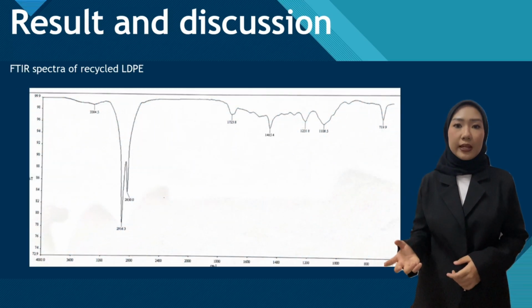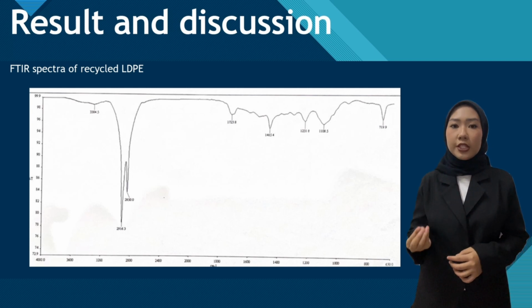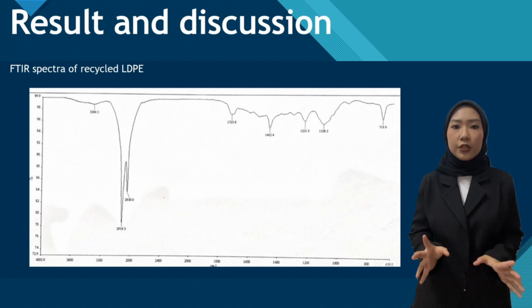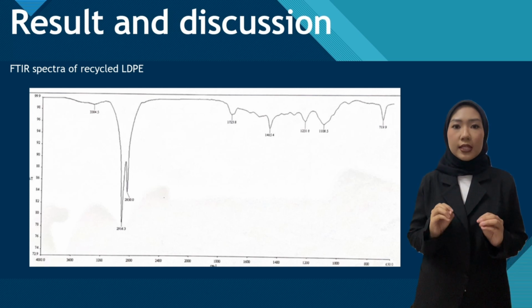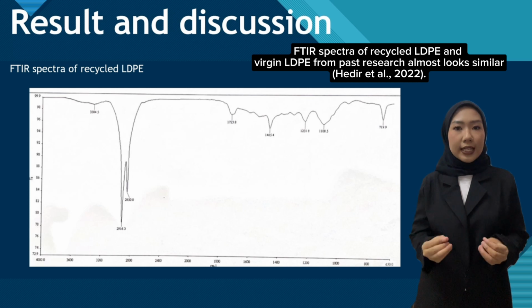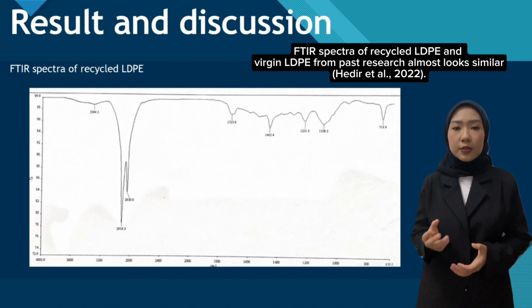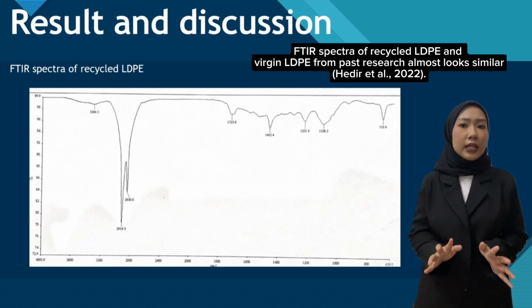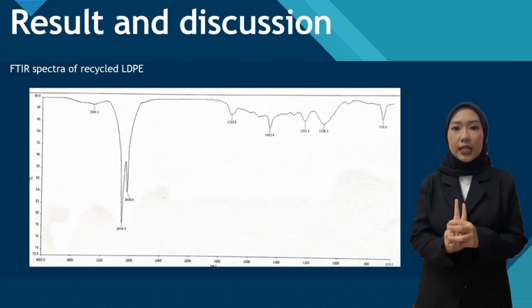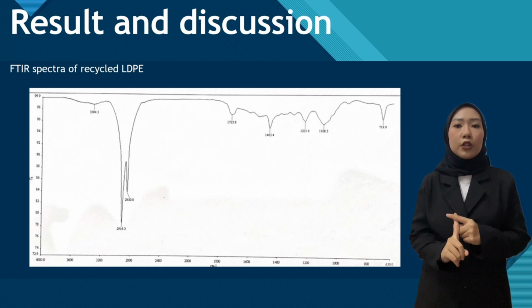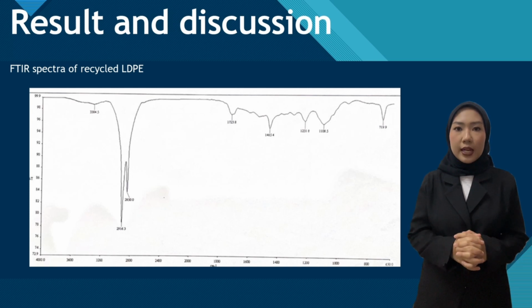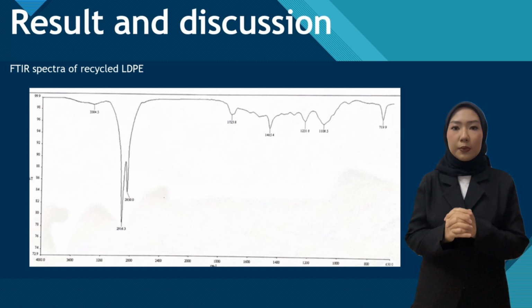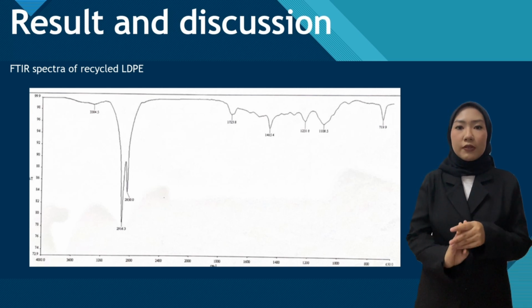The FTIR spectra of the recycled LDPE show complete, well-illustrated spectra. The CH2 stretching vibrations of the main chain were observed at 2916.3 cm inverse and 2850 cm inverse. The FTIR spectra of recycled LDPE and virgin LDPE from past research by Hadir 2022 almost look similar. However, there are 2 groups that differ between the virgin and recycled LDPE. Firstly, C double bond O stretching vibrations appeared at 1723.8 cm inverse, and the next is CO stretching vibrations appeared at 1231.8 cm inverse and 1108.5 cm inverse.